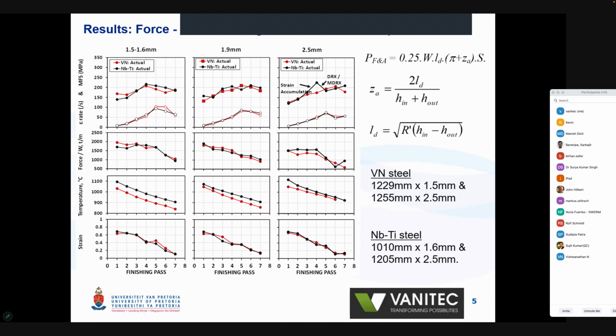So these are the results that we've obtained so far, a selection of results. The mean flow stress and force behavior was assessed using mill logs, and the Ford and Alexander roll force equation is shown top right over here, where the force is a function of width, contact length, Z, the arithmetic mean in terms of reduction, and then the stress. Z and contact length L are given by those two equations, which are functions of the roll radius and the draft. And you can see here I have plots of 1.5, 1.6 millimeter, 1.9, 2.5 millimeter, and I'm